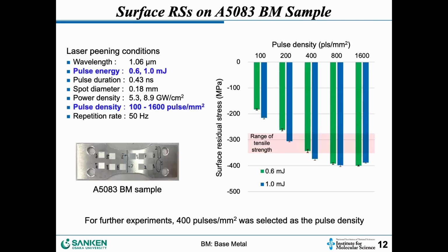So this one is the typical result for the A5083. We fixed the spot diameter at about 0.2 millimeter, and we changed the pulse energy, in this case 0.6 and 1.0 millijoule, very small compared to the conventional laser peening. And the pulse density is fairly high, 100 to 1600 in this case.